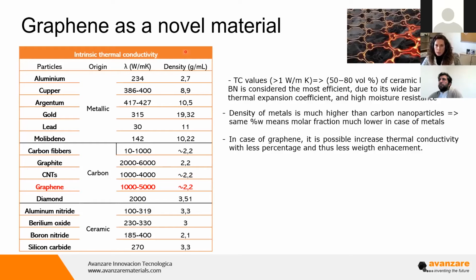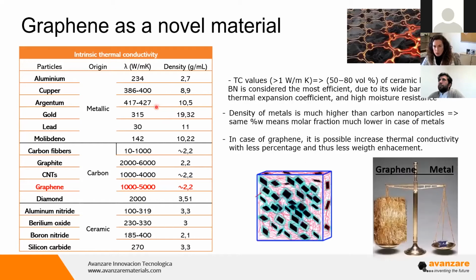For example, if we compare graphene density, about 2 grams per milliliter, with metallic nanoparticles, we are talking that this is about 2, 3, even 5 or more times higher. So this means that the density of metals makes it so that at the same percentage by weight, the molar fraction is much lower in the case of metallic particles. This can be observed graphically. If you remember, this is the situation that we need to obtain to have thermal conductivity. The graphene is dispersing and occupying much more than metal nanoparticles because of this.